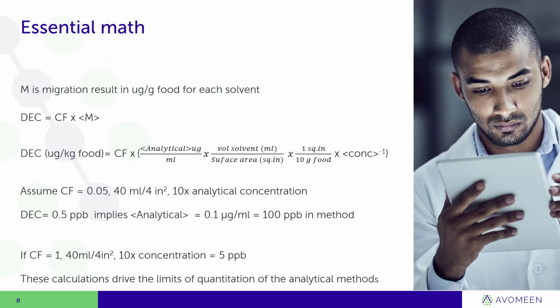For example, for materials that are used for infant formula bottles, the FDA will assume the consumption factor is 1 because it is reasonable to assume that an infant gets their entire diet packaged in this type of polymer. And so they don't allow this consumption factor, which is a factor to reduce the migration result into a dietary exposure. They don't allow any reduction. You assume that the entire diet of the infant comes from that package, and that's very realistic for an infant, and that's what's used.